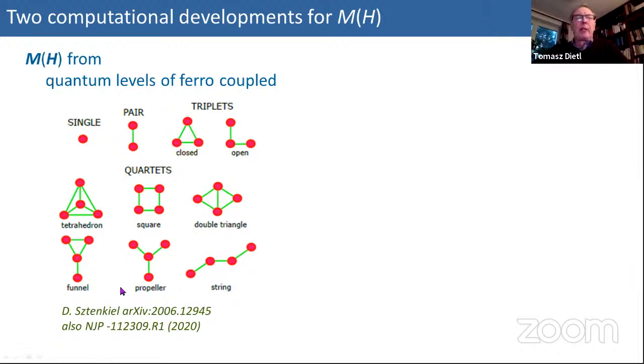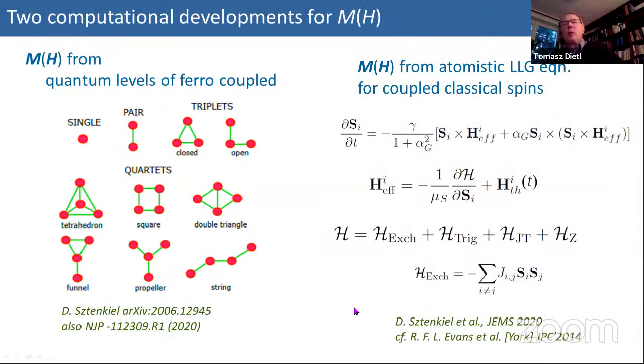And in recent papers in the Journal of Physics, he showed how he's successful in describing magnetization with this cluster approximation. And he also used another approach, which I like very much: he used the atomistic Landau-Lifshitz-Gilbert equation. Some of you know that nowadays people have computational means that do not describe macrospin properties, but you can solve this classical equation for individual spins and couple the spins by exchange interaction and see the time evolution of the system.